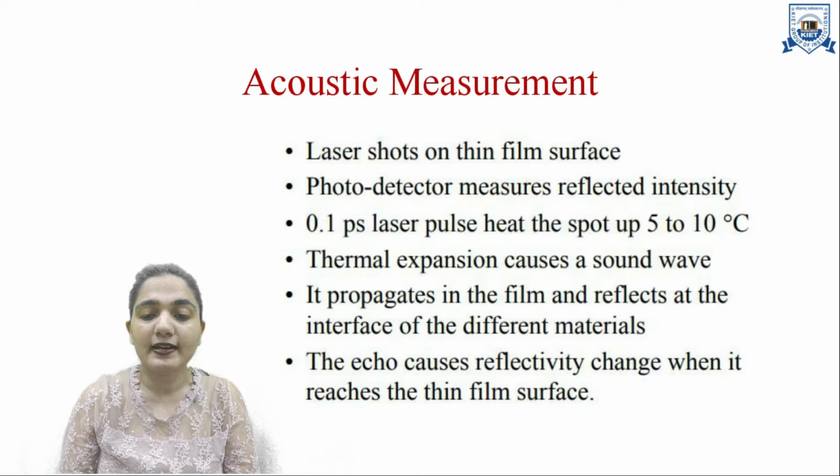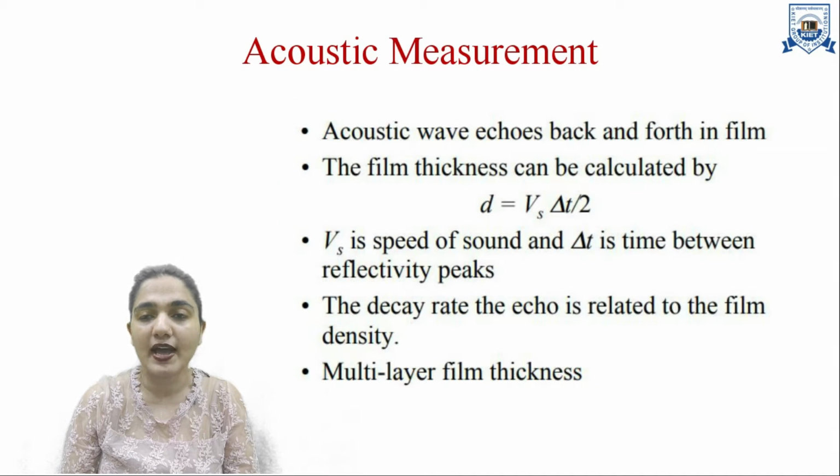A 0.1 picosecond laser pulse heats the spot by 5 to 10 degrees Celsius. So thermal expansion causes a sound wave also. It propagates in the film and reflects at the interface of the different material, and the echo causes a reflectivity change when it reaches the thin film surface, and this reflectivity change we have to measure.